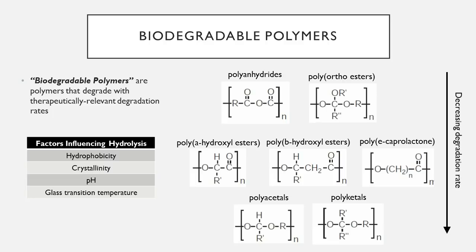Whenever drugs are incorporated into polyanhydride, they're distributed homogeneously throughout the polymer, but if only the surface is degrading, then the drug doesn't get released through diffusion, only through degradation. And because it's happening at the surface, it results in that nice, constant, even profile, a near zero order drug release profile.